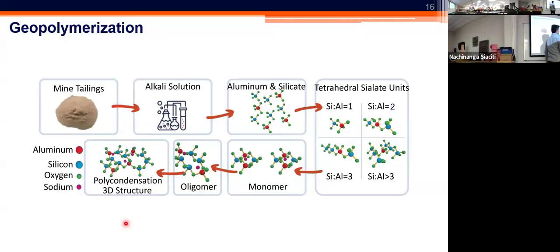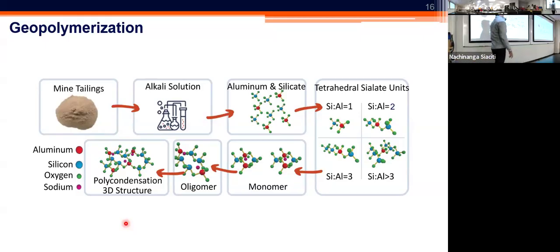and silicon species. Depending on the ratio of the silicon to aluminum, those released species can participate in the formation of the tetrahedral units. Again, whether you naturally have the proper range that can immediately produce those ideal units, or you can engineer the system by providing additional sources of silicon and aluminum, it is fairly easy to target different types of connections of the silicon and aluminum species.